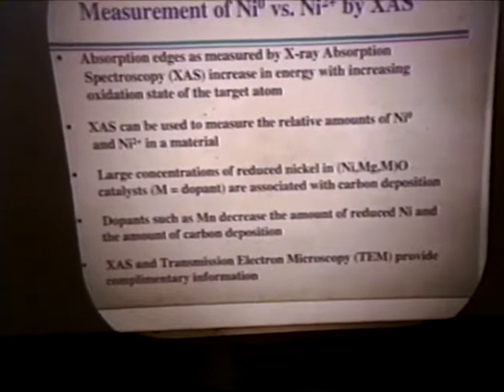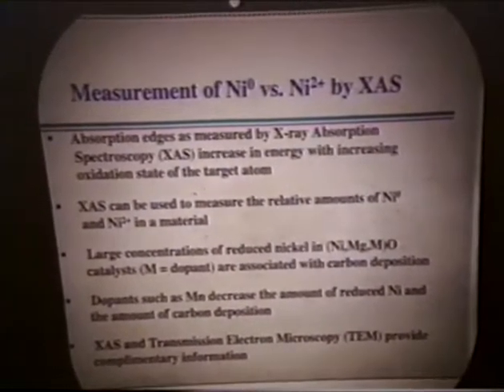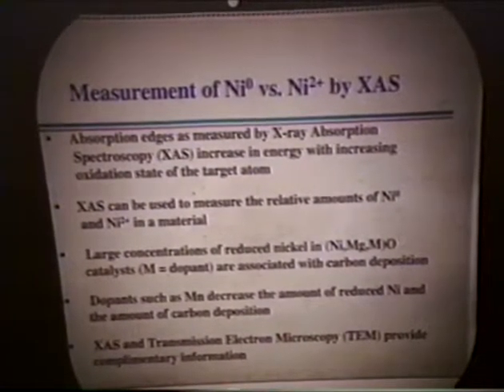So we also did some EXAFS characterization, because here we can quantify the oxidation state of nickel plus 2 versus nickel 0 and know the extent of reduction. So we thought this would be a nice way to couple our analytical with the XRD that we looked at earlier. And we found that without a promoter, yes, you do see some reduction of your nickel plus 2 to nickel 0, whereas with a dopant, this is not necessarily the case.